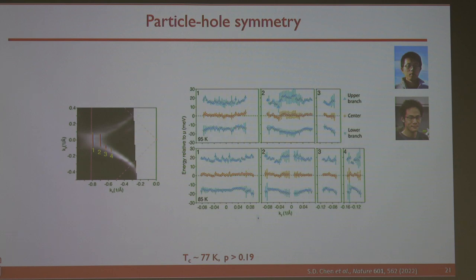But what I want to say to you is that, in fact, if the experiment gets better, there are more than one gap in the normal state. One of these two, which are being focused on, is the gap due to preformed pairing above TC. But now I'm going to show you evidence of the second gap, which is related to the higher energy scale, which is the residual of the Mott insulator. Okay.